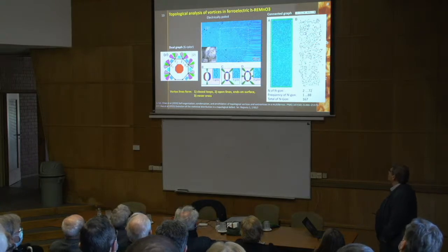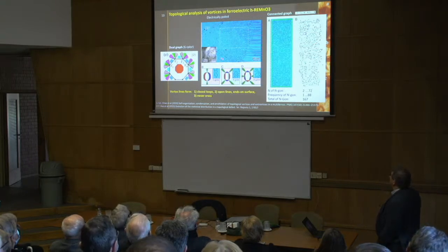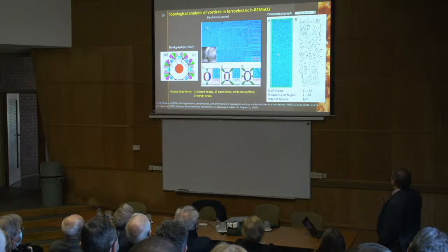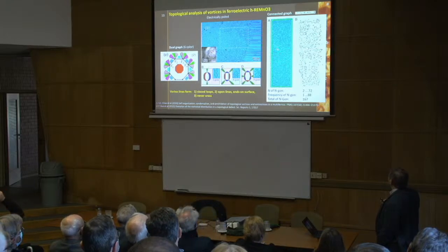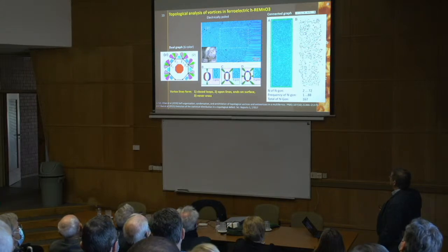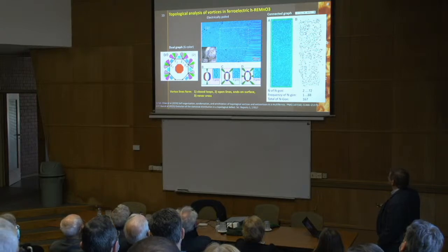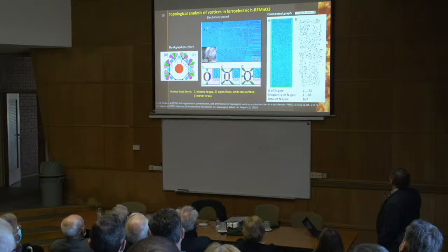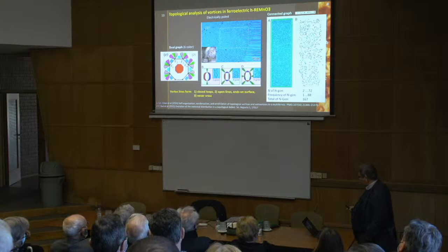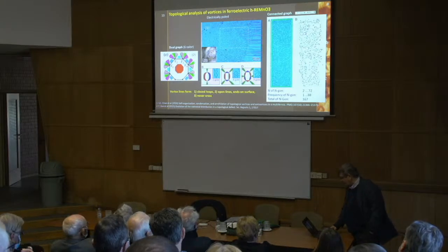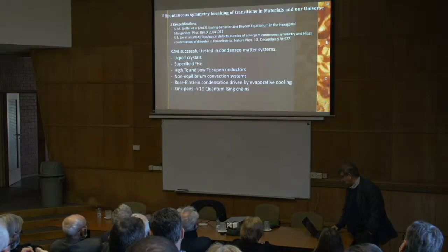Okay, just a very rapid overview on topology. This is how, in a single case, you can see all these domains, all the vortices. This was poled, so the positive domains are expanded, the others too, but the vortices do not move. This is a topological representation, the dual graph, where every point represents one of these vortices, and 6 colors, because there are 6. And this is the counting done by Xue, to demonstrate that the topology was there, it was 6-fold, or we may say Z2, Z3 symmetry.